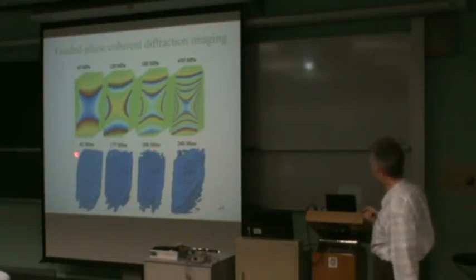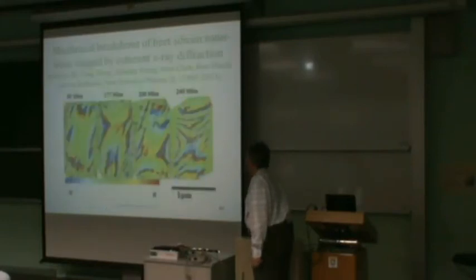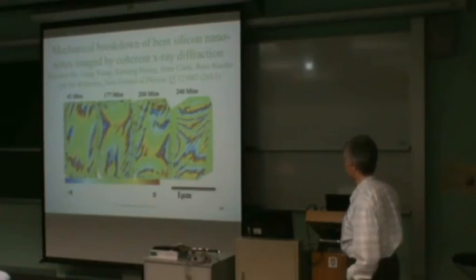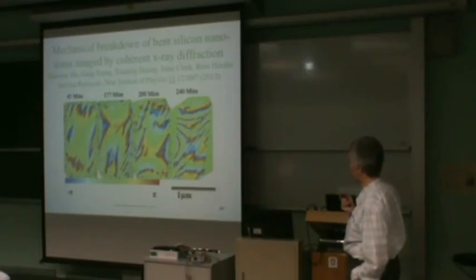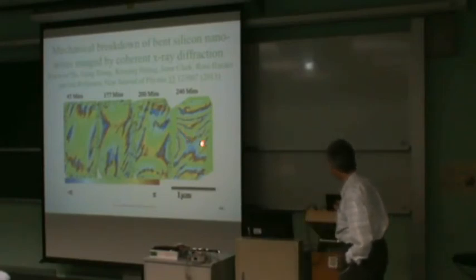And you can see that you get phase distributions which, this is the input phase for the reconstruction of this object. And the amplitude comes out a little bit broken up, but mostly filled in. You've got ragged edges where the edge of the beam occurs, but you've got a fairly good reconstruction of a solid piece of silicon, but the phase is actually quite rich. So what we are seeing, and some of this is noise because the data are a little bit noisy, is at 45 minutes a relatively unstrained pattern with a little bit of strain at the edges. The strain moves in at later times and further, and at 240 minutes, which is the last one before the diffraction pattern disappeared, we're seeing quite rich zigzag-like phase structure inside the wire.